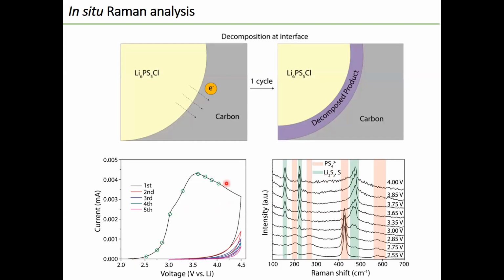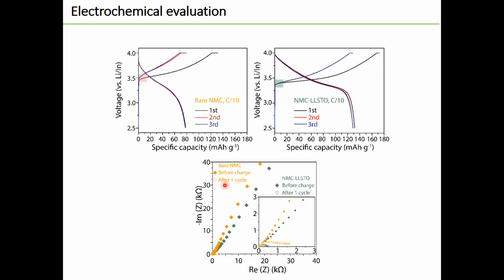After that, we assembled the cathode and the electrolyte in a cell to evaluate the electrochemical performance. In bare NMC, we can find the initial charge voltage is higher than NMC with coating, and after one cycle, there is obvious overpotential, but in NMC with coating, there is no overpotential after one cycle, which proved there is a severe reaction between NMC and the electrolyte.